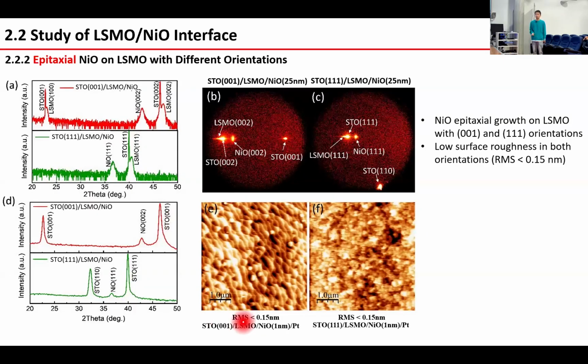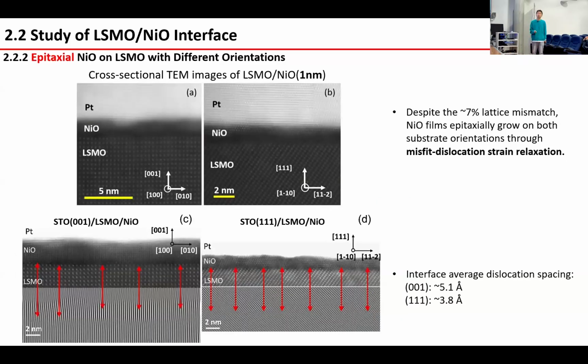And the devices of the LSMO, nickel oxide and platinum, the 3 layers, also show a very flattened surface as well. Here we also show the HAADF image of the epitaxial growth on both orientations, the 001 and 111 oriented, where the nickel oxide is quite continuous at 1 nanometer, and a clear and sharp interface is obtained as well. One thing to mention is that despite the 7% mismatch between the LSMO and nickel oxide, it could also achieve epitaxial growth due to misfit dislocation strain relaxation.